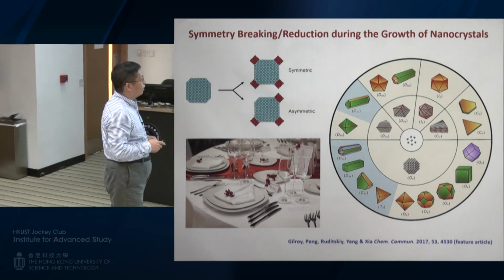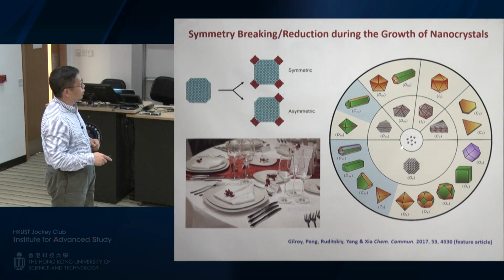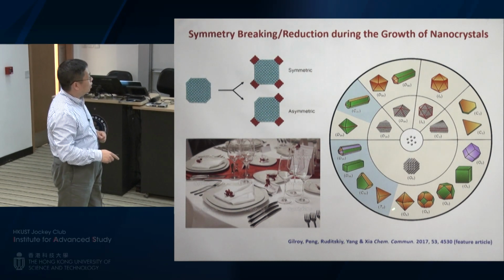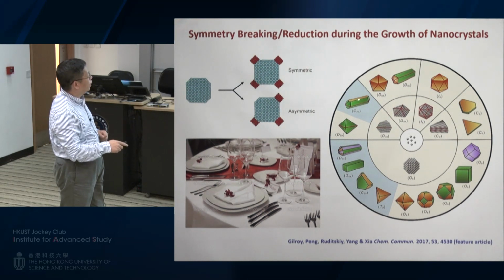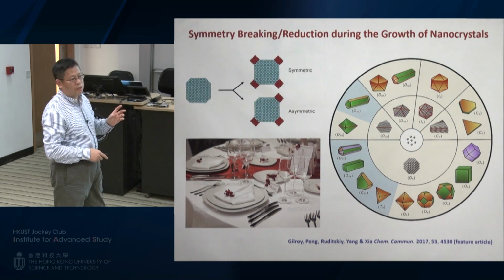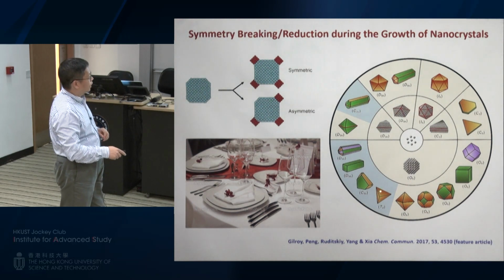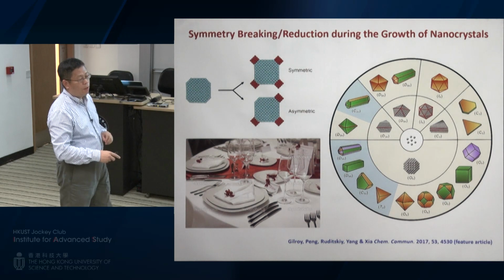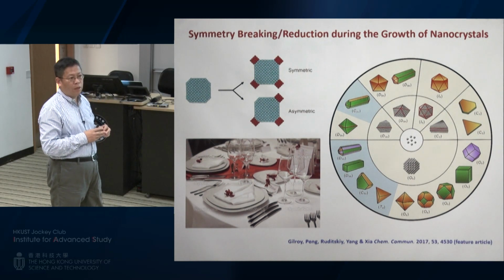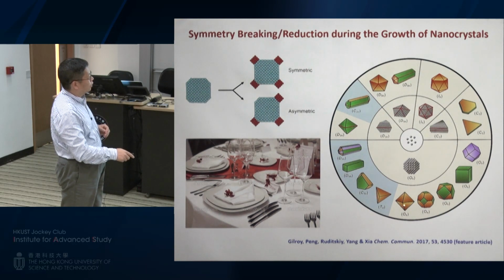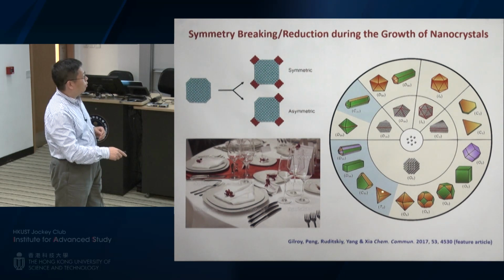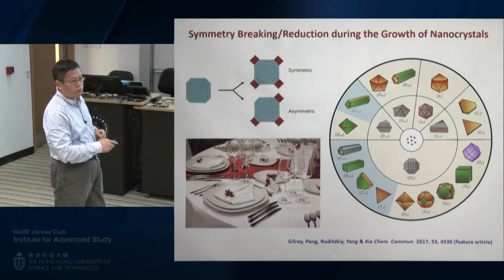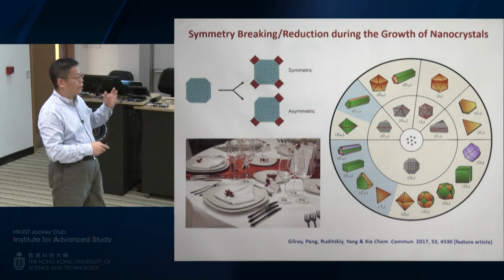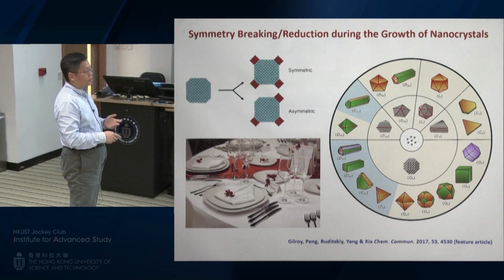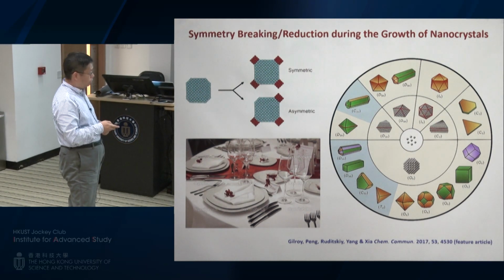Okay. So now let's come back to take a look at the illustration I showed you earlier for nanocrystal growth. In fact, we can single out those particles in the gray area. And these particles are supposed to be equivalent to these guys. The only difference is their symmetry is much lower. For example, this tetrahedron. The tetrahedron is related to this octahedron because their surfaces are the same. They are 111 facets. However, symmetry-wise, this is lower than octahedra. So you can imagine this is a product of asymmetric growth, and this is a product of symmetric growth in this case. So basically, we can start to achieve an even better understanding of why certain shapes are formed during the growth process.